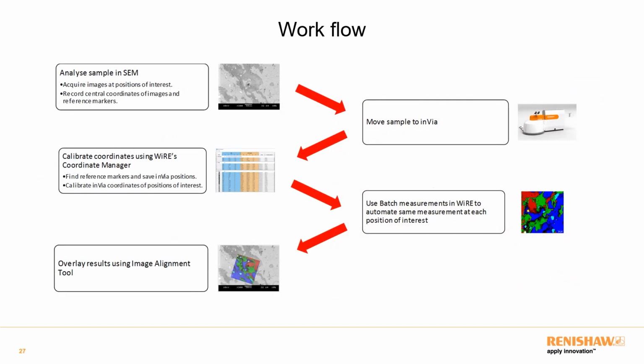So what's the workflow for this? First of all, we analysed the sample in the SEM. We took images at regions of interest, and we recorded coordinates based on the centre of where those images were taken. We then moved the sample to inVia. We calibrated the SEM coordinate system to match the inVia coordinate system using the coordinate manager. And then we're able to conduct batch mapping measurements in Wire to automate measurements at our chosen positions. Finally, once we've got the inVia data, the Raman data, we can just overlay it directly with the SEM image.